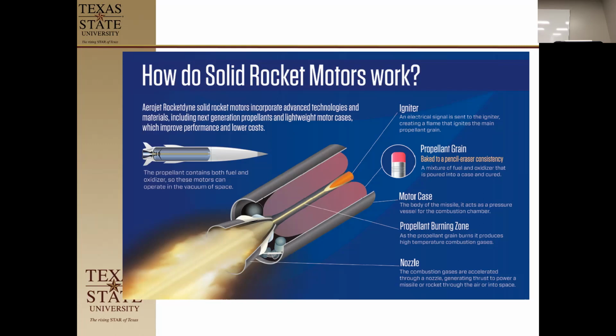You don't want it to crack, because if you crack, you're changing the surface area. If you change the surface area, you change the thrust dynamics. And that's why solid rocket motors blow up. If you have a crack anywhere in here, it's going to burn into that crack. Then you're going to be closer to this edge than you should have been during burn time. And you're going to either burn through the side, or it will actually explode because it will create so many more gases that it comes to the nozzle.